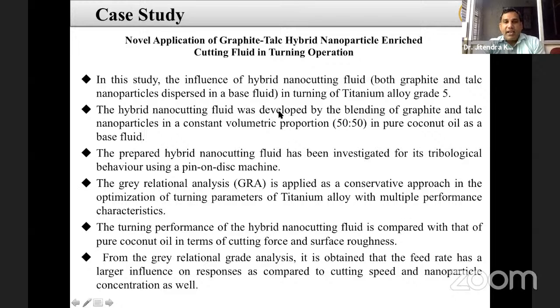In this study, I formulated the 50-50% proportion of these two nanoparticles in coconut oil as a base fluid, and used it in minimum quantity lubrication. I chose titanium alloy grade 5, which is widely used as medical grade. Machining titanium alloy is not easy, if you want better surface finish and better tool life.